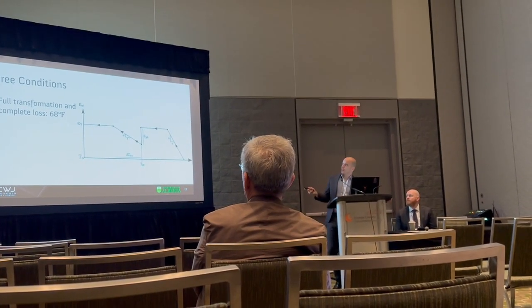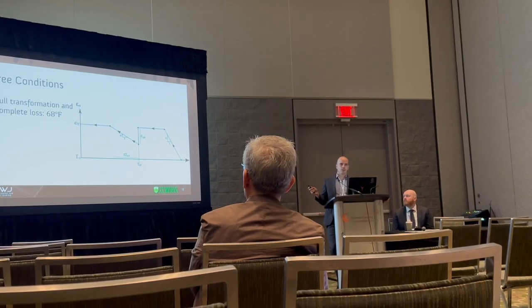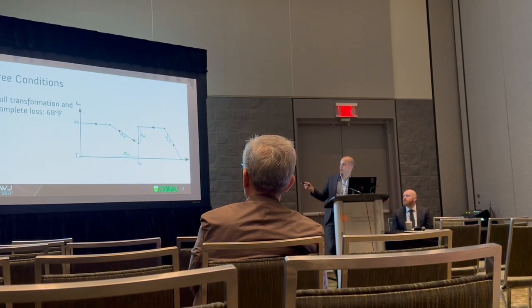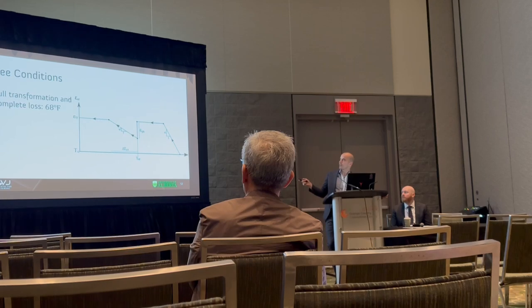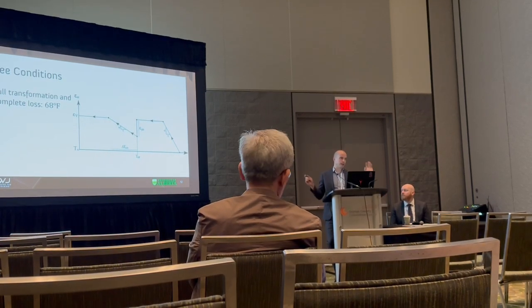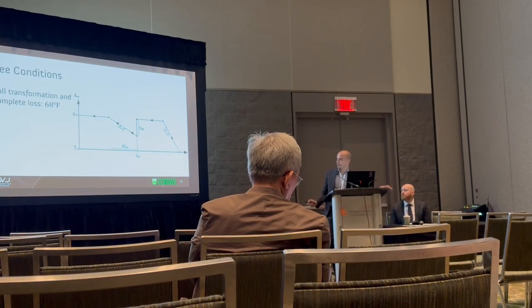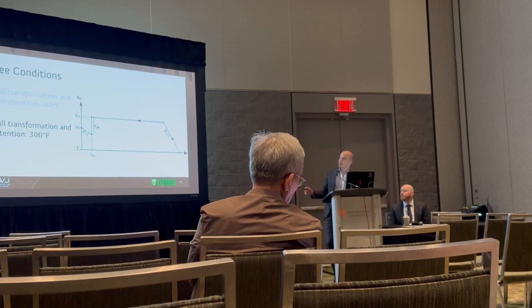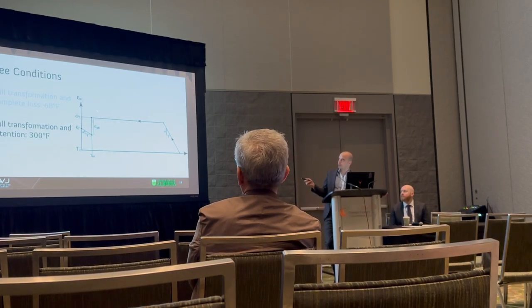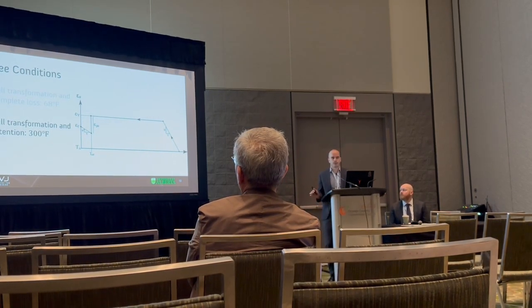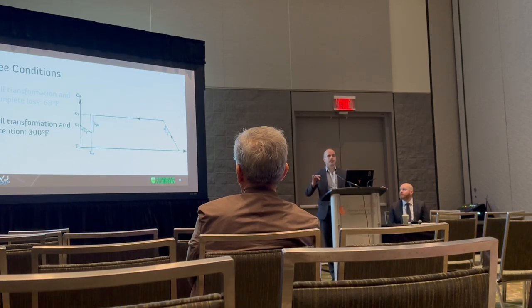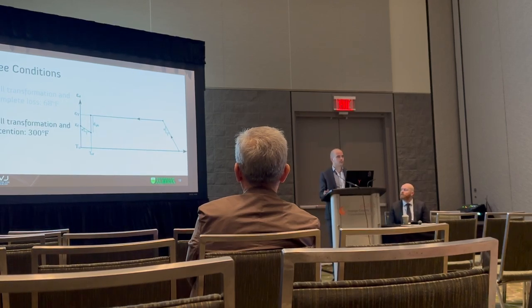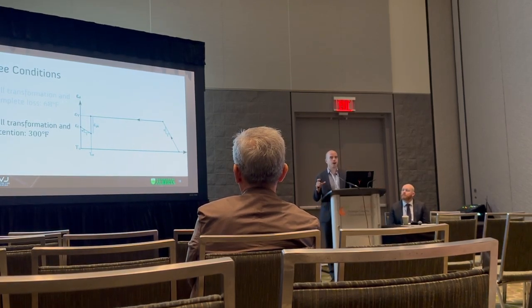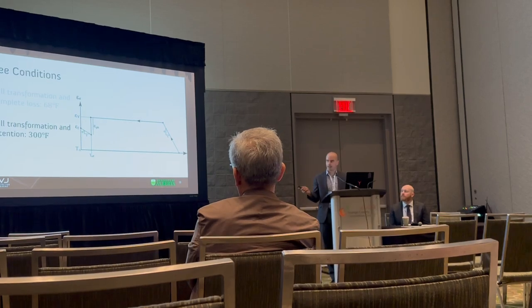Like I said, at 68 degrees Fahrenheit, we're outside of our critical allowed temperature, and it's exactly what I showed you earlier. The martensite transformed, and then it contracted and it yielded, and we're back where we started. We might as well have not had the transformation from a stress point of view. But then we've got this one at 300 degrees Fahrenheit. We've completed the martensite transition. Also, for metallurgists who want to be upset with me, 95% martensite is what I'm calling complete here. So it's a complete transformation, and it contracted a little bit because we're past that martensite finish temperature, but not enough to reach that critical stress that I talked about.